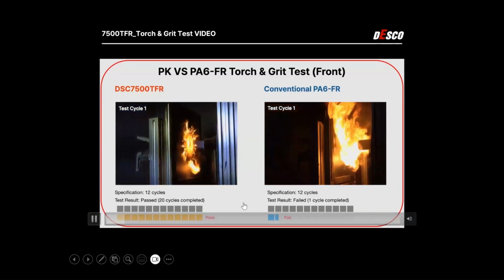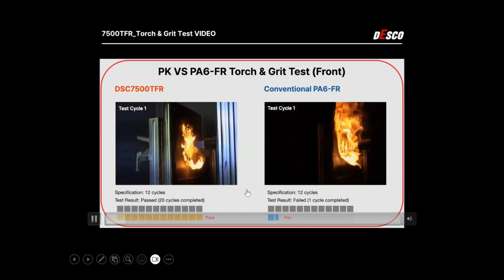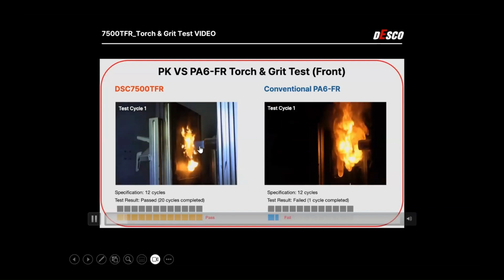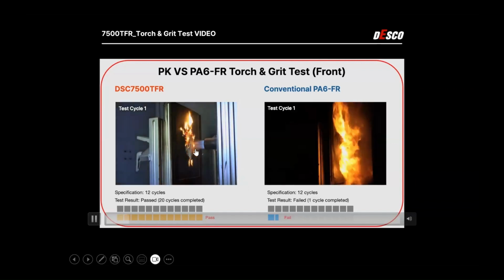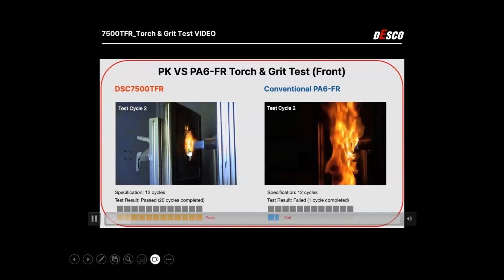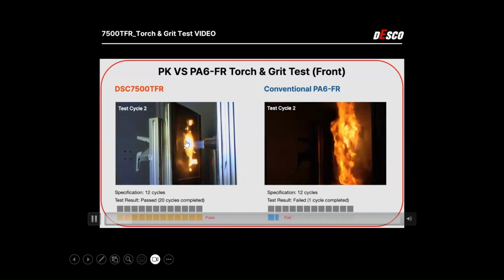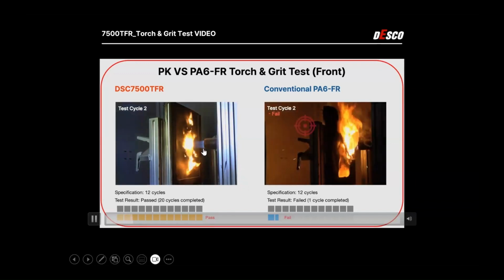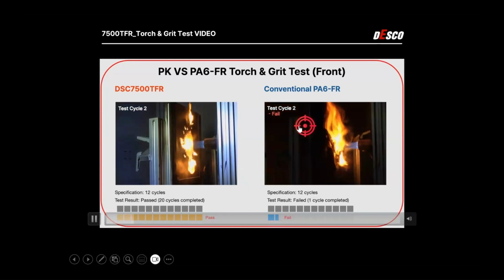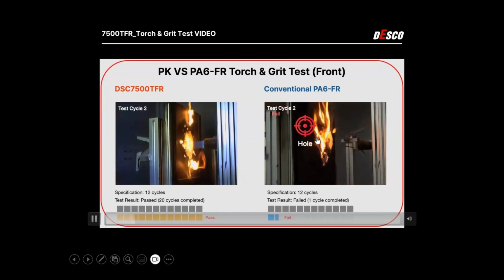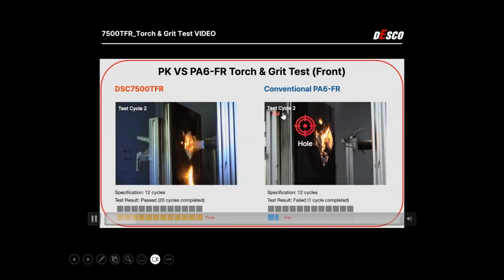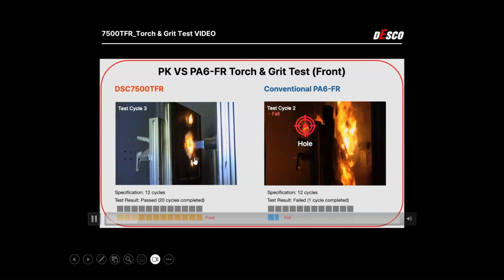This is one cycle. After 15 seconds, there is aluminum grit over here right now. And now it's cycle 2. It repeats for 15 seconds and 5 seconds. And as you can see, the nylon flame retardant grade already had a hole during cycle 2. So we stopped it. But this is the polyketone TFR grade.